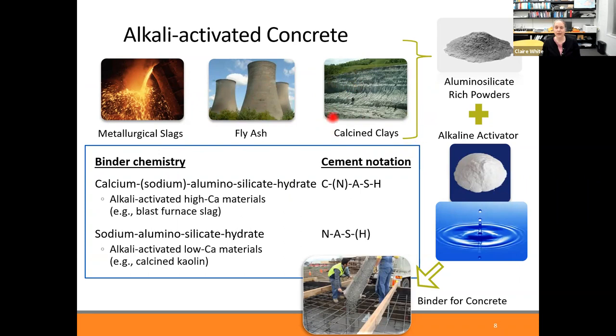But say if you add calcined clays to water, they're not going to react. So we need to activate the clay to get it to dissolve, and then for a mechanically strong binder phase to form, to give concrete strength. And so we use an alkaline activation process, for example, a sodium silicate, a high pH system.